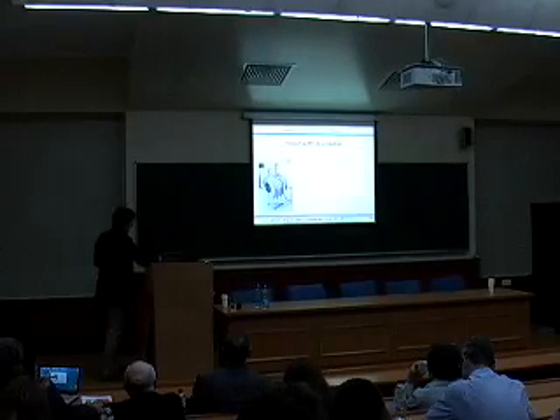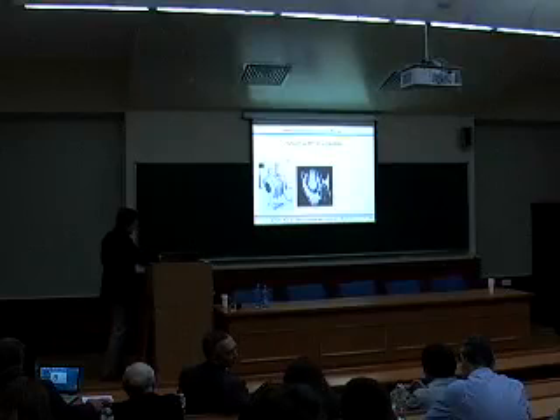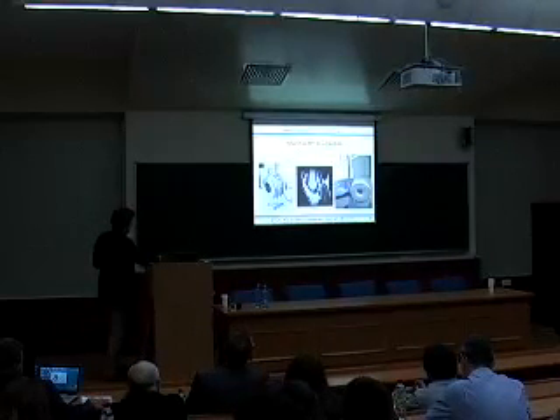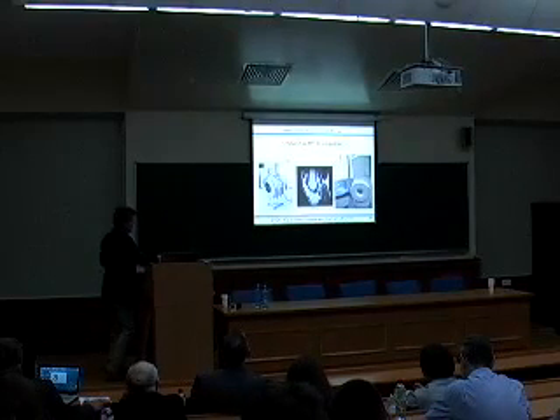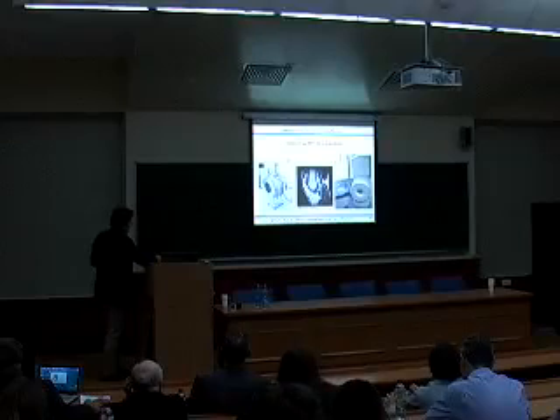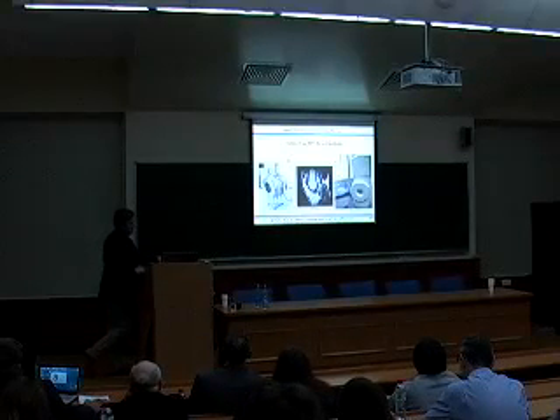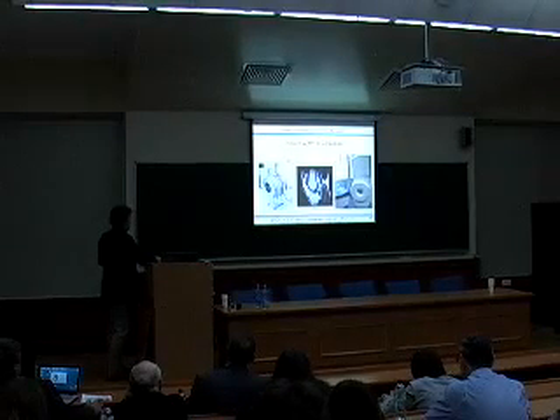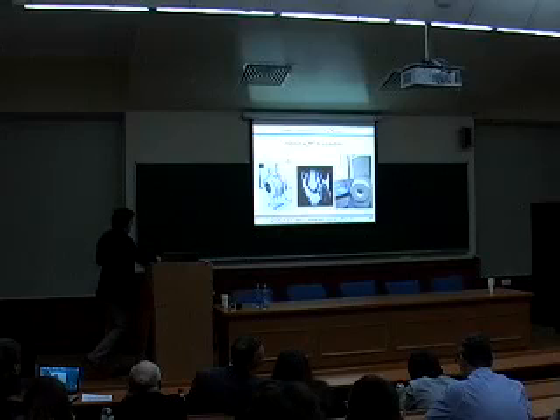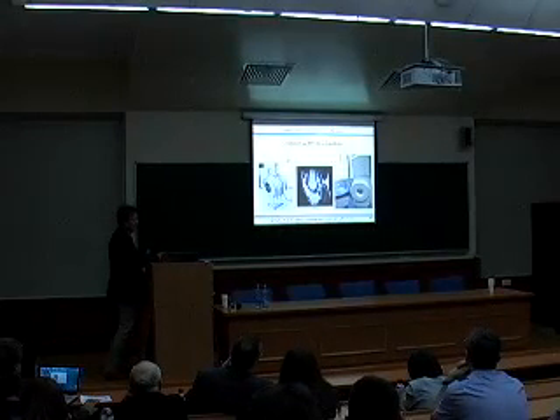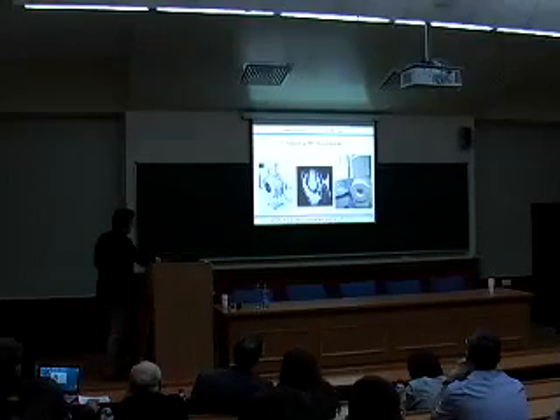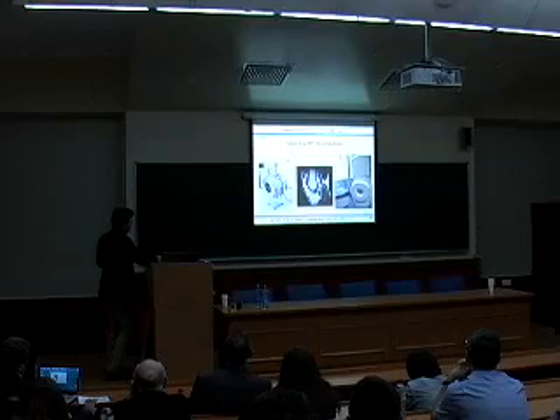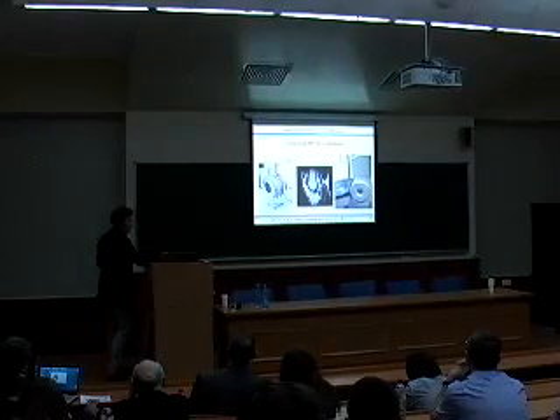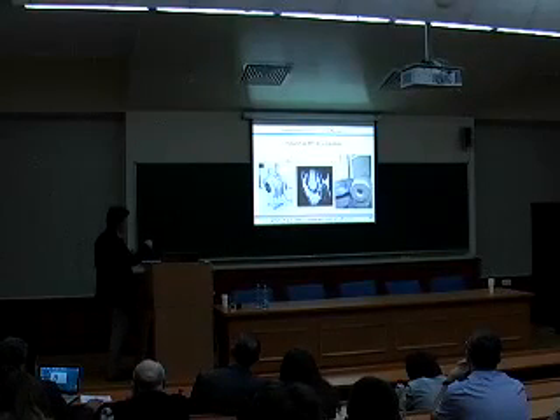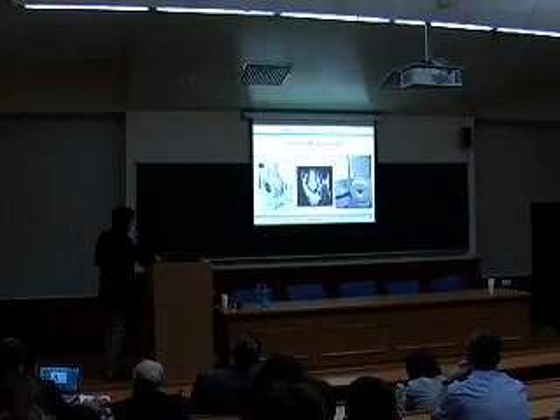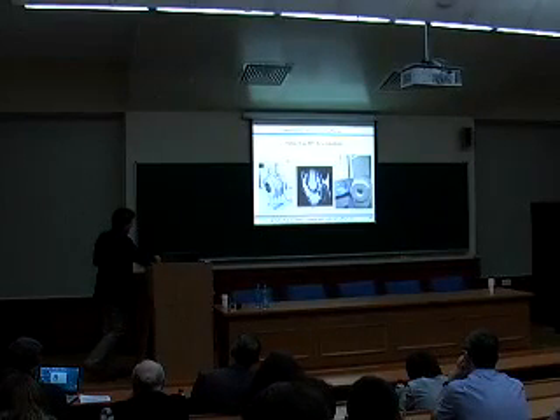Important is this picture, because here we realized helium-free technology. It means that inside of the helium vessel we have no helium. It's vacuum. And it is the so-called conductive method of cooling. We cool not the superconductor directly, but we cool the support for the superconductive wire. It's working very safely.